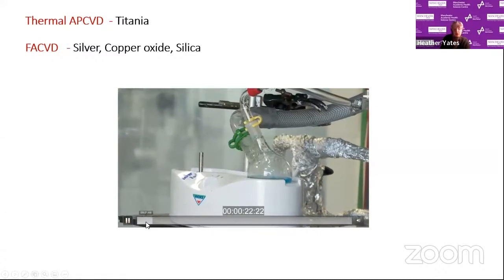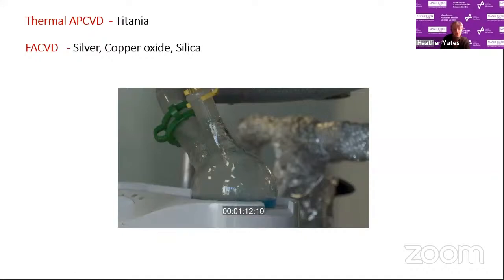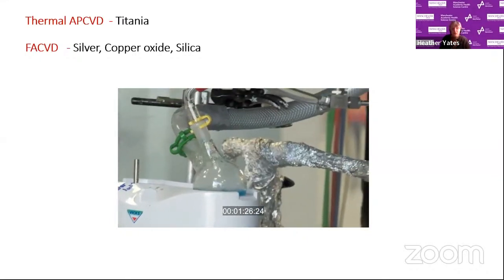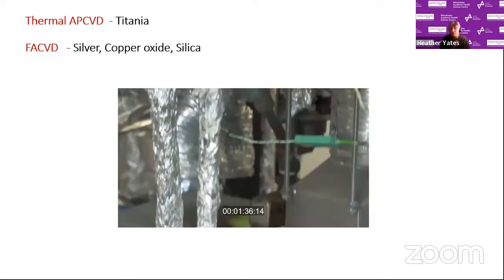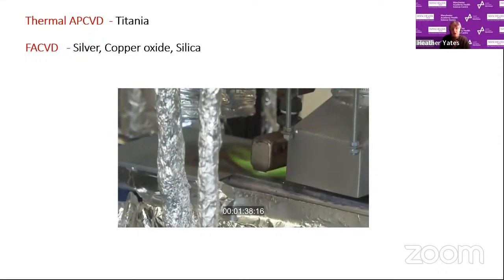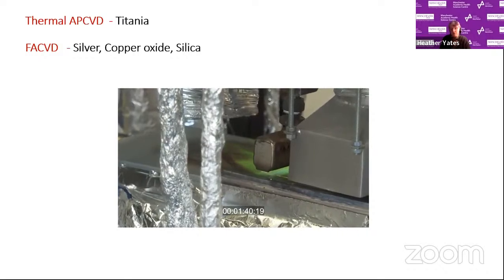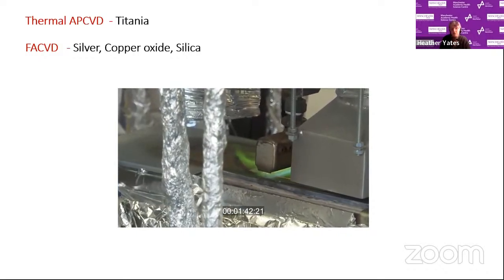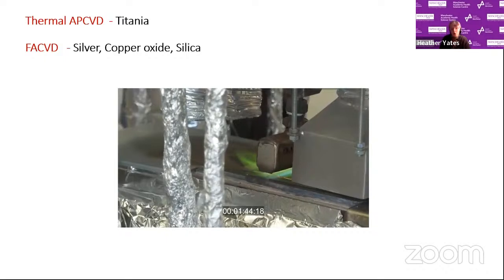So basically I have a nebulizer with the liquid which forms a mist. And you can see it's this kind of misting up inside the beaker. That's copper sulfate in there in water. And I will be passing through that nitrogen. So it will take the nitrogen and the mist into my reaction area where it goes to a coater head along with a propane flame. And you can see there the green flame. It's green because of the copper.